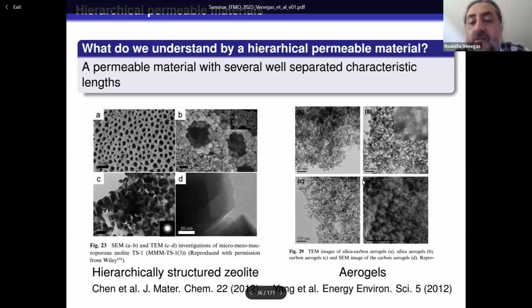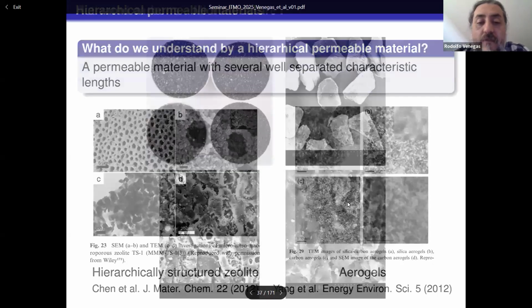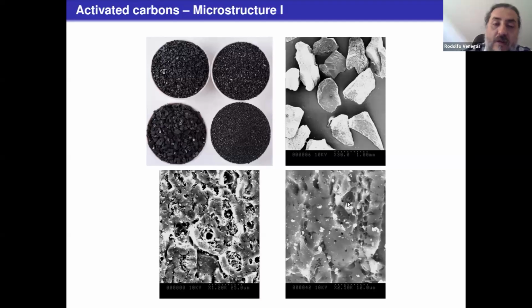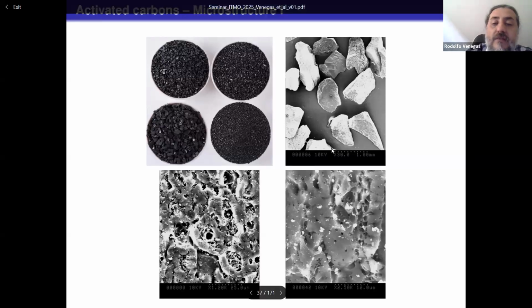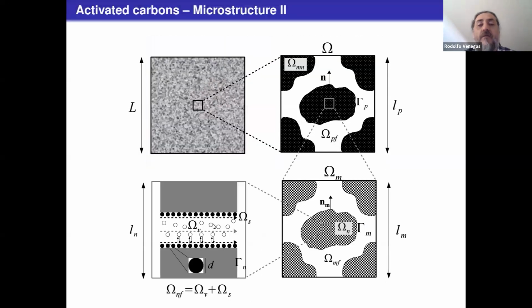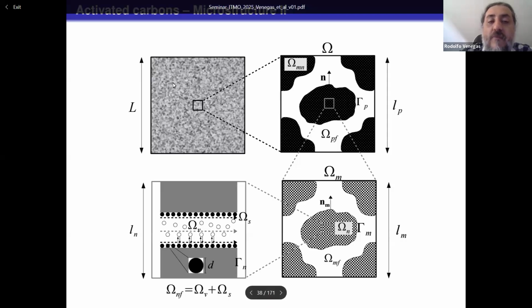With aerogels, it's a similar picture, but we have focused on investigating activated carbons for quite some time. This is a particle of activated carbon, and these are SEM images of the surface of these particles. So we have lots of pores on the order of 1 micrometer on the surface of these particles, and some of them are even larger, like 5, 6 micrometers across. So we can think of activated carbon as a material with a triple porosity, where we have a macroscopic scale, one porosity associated with what's happening around these grains. The grains are in black.